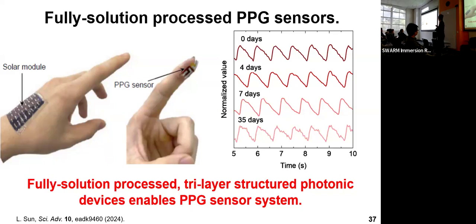And an important achievement is the storage stability in ambient air conditions. Even after one month of storage in ambient air conditions, our integrated systems could be operated almost normally. You can see small noises in the aged devices, but still we could see the heartbeat signals from these aged devices. So this means our solution process devices can be stored in ambient air conditions. So maybe this can be useful for practical applications. So we don't need the glovebox systems to store the devices.